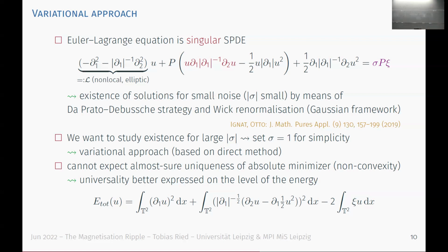But then if you look at this term here, you can work out what this term is. Then you see that essentially what you're trying to do is multiply an object which is of negative regularity by something that is of positive regularity, but not enough regularity to make sense of this product. So that's why this Euler-Lagrange equation is a singular stochastic PDE, but using some of the standard theory, using a renormalization procedure, which is here in this case just a mild renormalization, you can do a small noise theory by means of a fixed point argument.